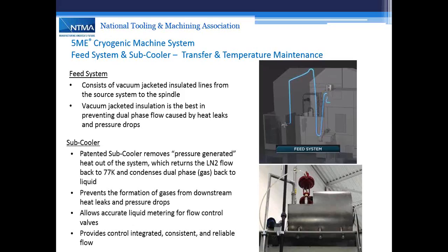and if you were to run a standard cryogenic system, what would happen is you get a puff of gas and then some liquid flow and then another puff of gas. In normal cryogenic uses for bottling plants and the food industry, that's not a problem. But when you're machining and you have a piece of carbide embedded in material at 800 degrees Celsius, you do not want to go from liquid cooling to gas cooling. Gas cooling is not efficient, and it will not extract the heat required. You will actually damage the edge, and it's obviously not recoverable, and the wear increases from there. Next slide, please. So that subcooler was a patented added feature to the system to make it more efficient for machinability.